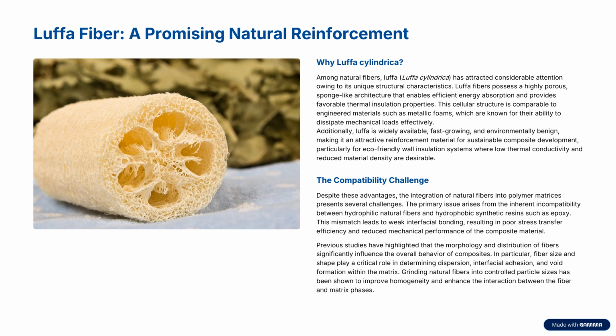Despite these advantages, the integration of natural fiber into a polymer matrix presents several challenges. The primary issue arises from the inherent incompatibility between hydrophilic natural fibers and hydrophobic synthetic resins such as epoxy. This mismatch leads to weak interfacial bonding, resulting in poor stress transfer efficiency and reduced mechanical performance of the composite material.